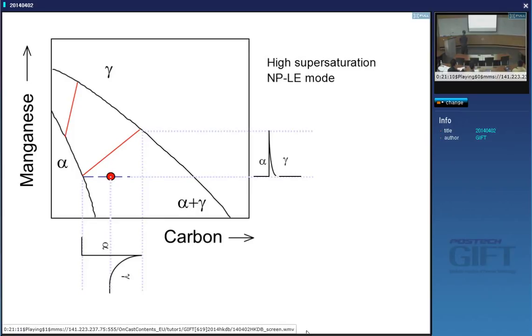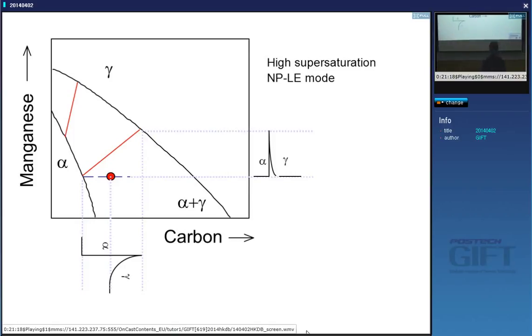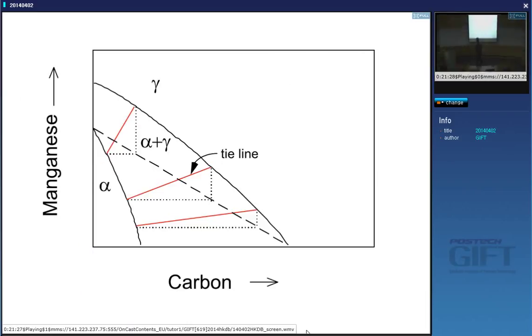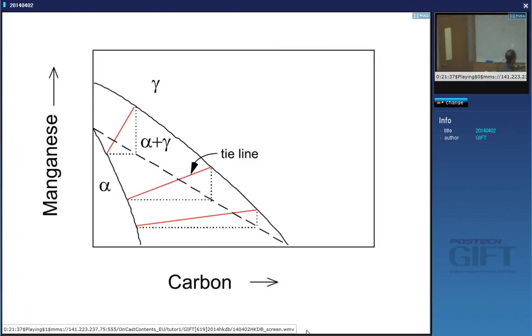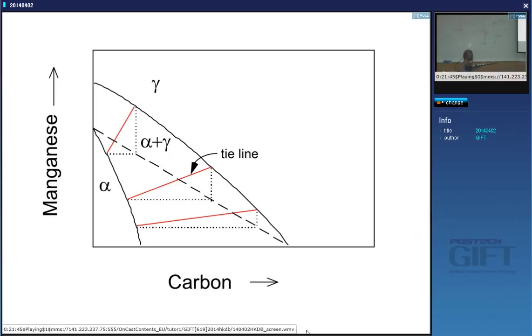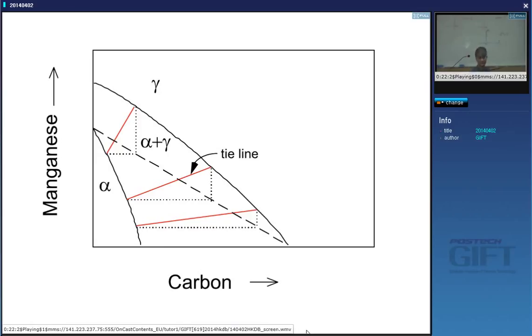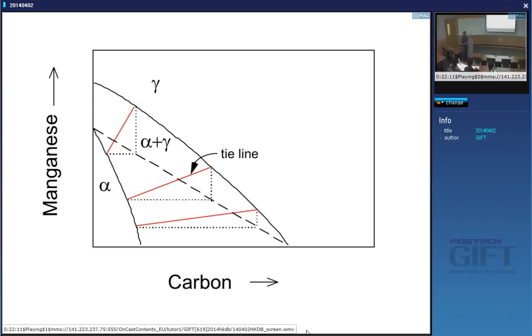This gives us a way of dividing the two-phase field into two regions. If we take the tie lines and draw right-angled triangles and join up the vertices, in one region you will get partitioning of manganese — that two-phase field contains the information. Join up the vertices of all these triangles: in the region near the gamma boundary, you get partitioning local equilibrium with long-range diffusion of manganese, so it will be a slow reaction. In the other region, the reaction will be fast because we are not partitioning much manganese.